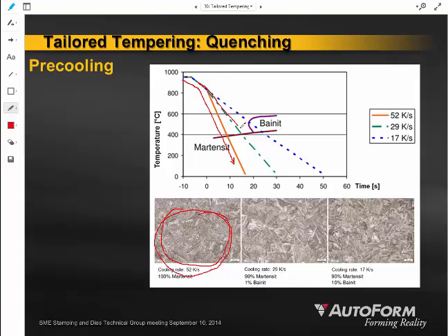If you cool the material a little bit slower, now you don't have 100% martensite. Maybe you end up with 99% martensite, 1% bainite, and that's going to give you a different characteristic in the finished part. And then if you cool this at a much slower cooling rate by holding that die a little bit warmer, then you're going to have maybe only 90% martensite and 10% bainite. And that material is going to end up being, as far as its strength, closer to that mill spec original strength of the material, as opposed to being that tempered, highly quenched strength that we get when we were talking about the martensite.